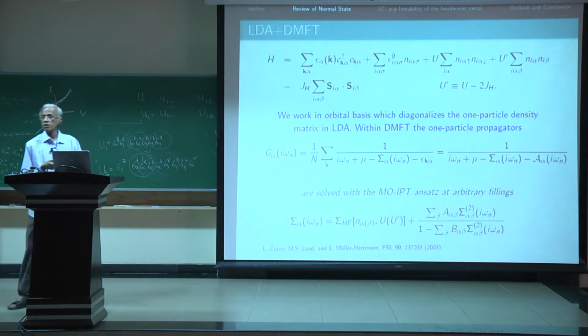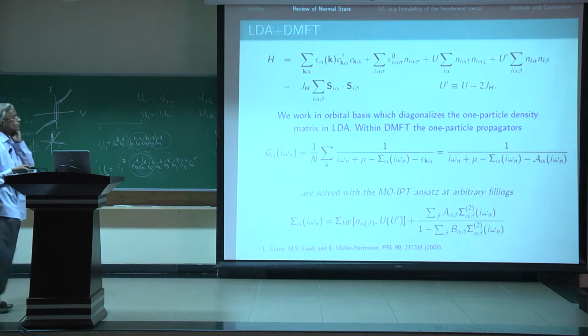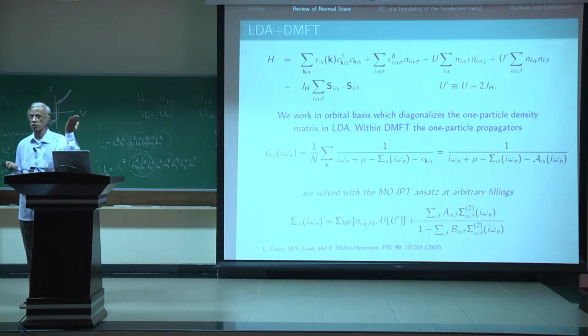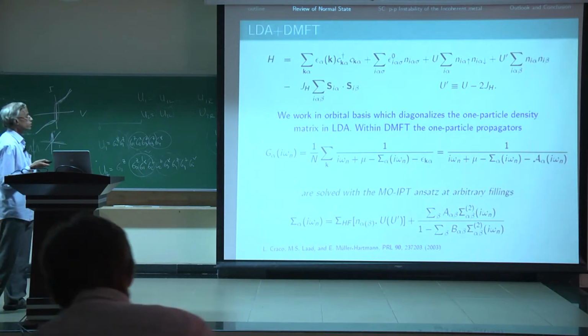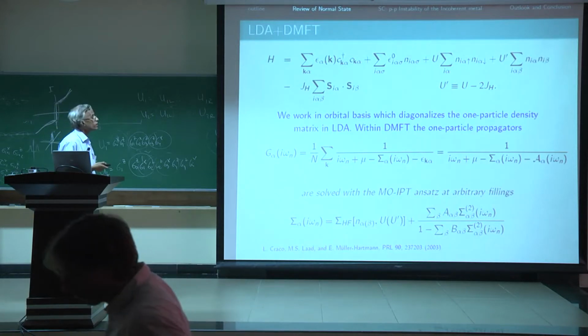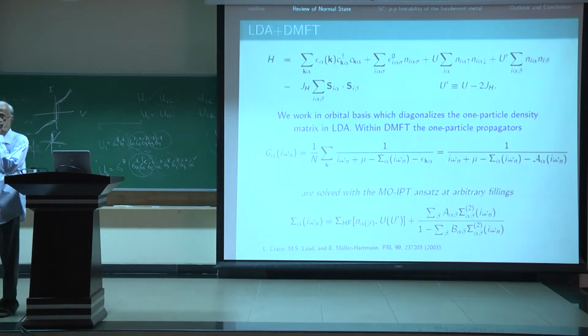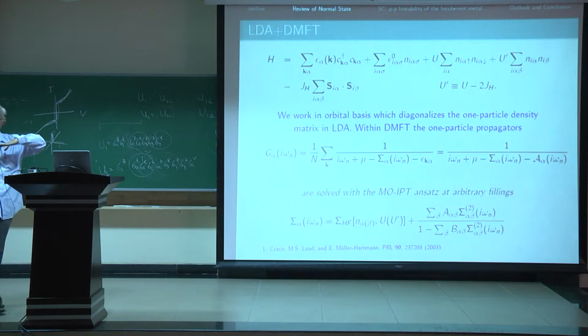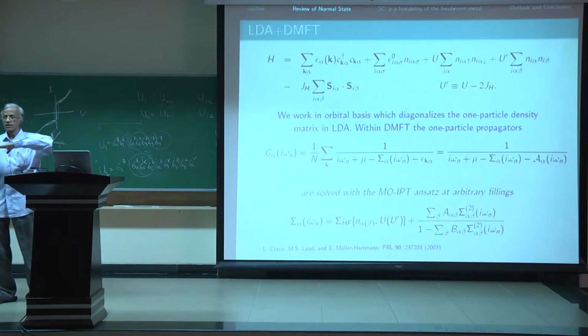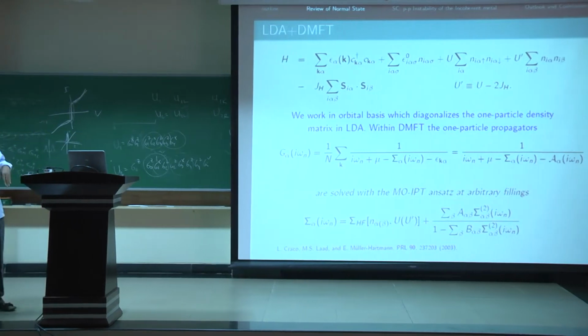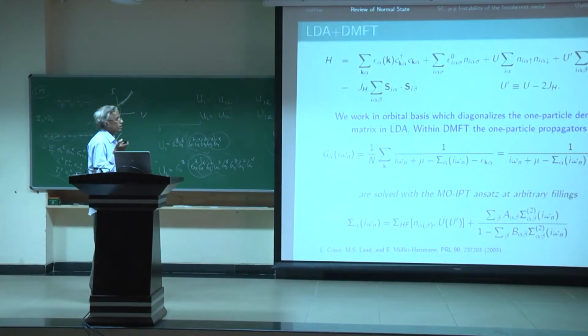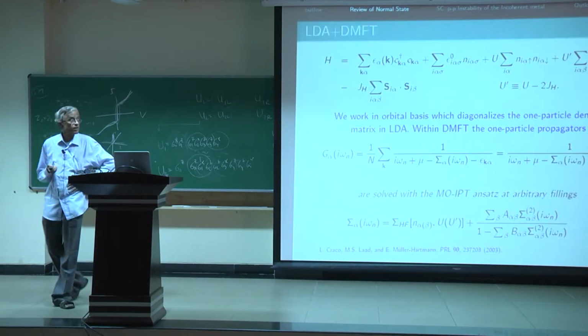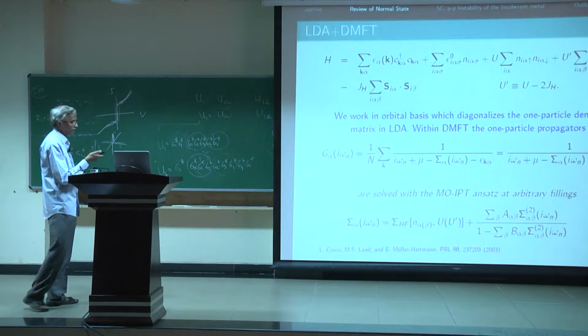Beyond those stages, how many electrons? 6. And you are adding electrons when you dope cobalt to iron, for example. But it is 6d electrons, and the xz, yz orbitals which are degenerate are partially filled. So there is an intrinsic propensity to basically break this orbital degeneracy, and I'll come to that.